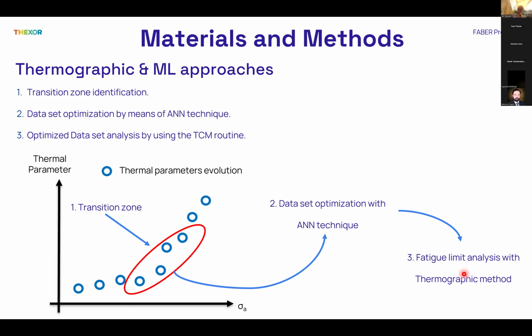This slide tries to explain and summarize how the thermographic method was combined with the machine learning approach. The thermographic method was adopted to detect and investigate the thermal parameters evolution as a function of the stress amplitude. Then the transition zone was properly optimized using the artificial neural network technique, and this optimized dataset was adopted inside the two curves method routine for the fatigue limit estimation.